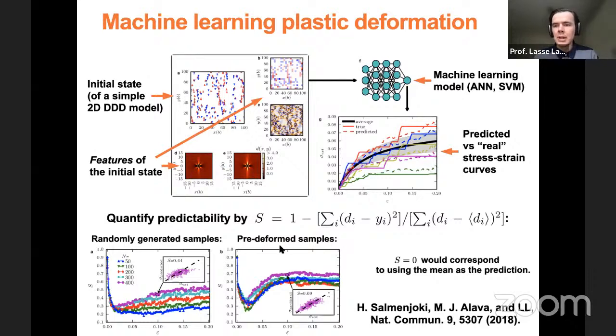Then we also generate a different data set to analyze, which is what we call pre-deformed samples. Instead of just starting from the initial randomly generated configurations that we let relax and then apply stresses, we first apply stresses up to some strain, and then let it relax again. We use those relaxed configurations as our initial configurations for the simulation. So these samples have some deformation history, they have undergone some deformation before the actual test that we do. And you see that this seems to have some kind of an effect. The curves here are a bit different, so the deformation history seems to affect predictability in some way.